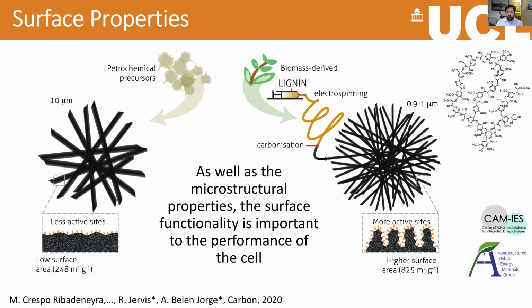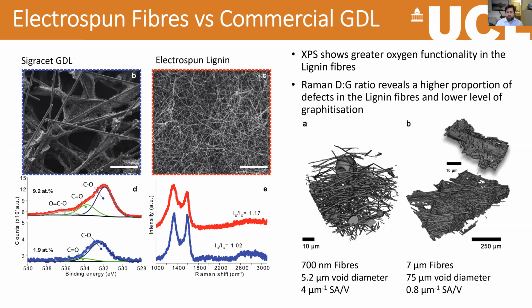So we've done a lot of work on this, and we're continuing to work with Queen Mary and Imperial as well on these kind of systems. And this just shows that we can get very different surface properties for these electrospun fibers, but they have very different flow characteristics as well. So we need to think about optimizing both the microstructure and the surface chemistry of these materials.